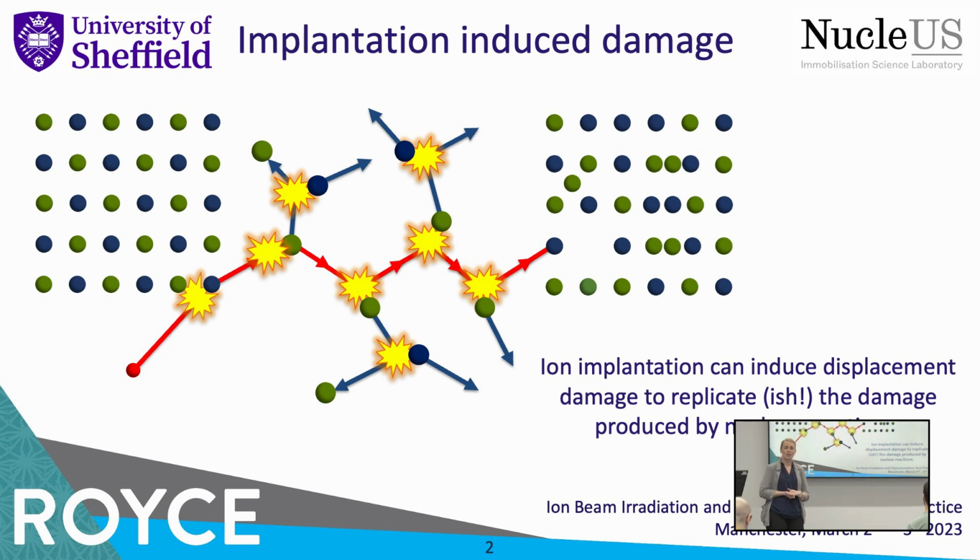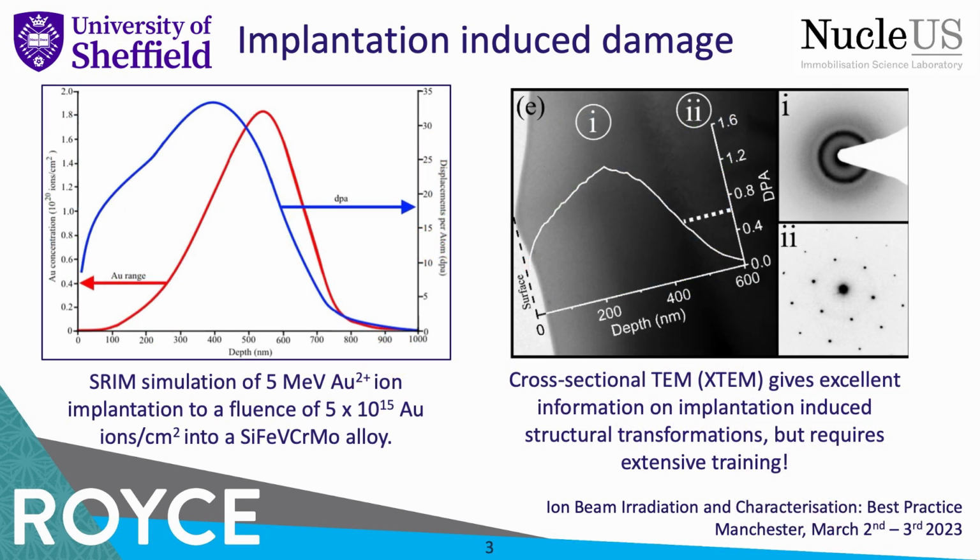other types of radiation, but ultimately it can induce structural modifications as well as form radiation-induced defects like dislocations, like Jack was talking about, gas bubbles, secondary phases, precipitates, and all the things that we've seen wonderfully in using TEM.